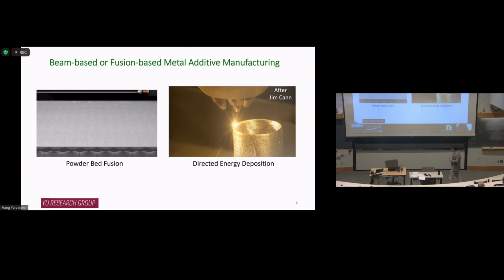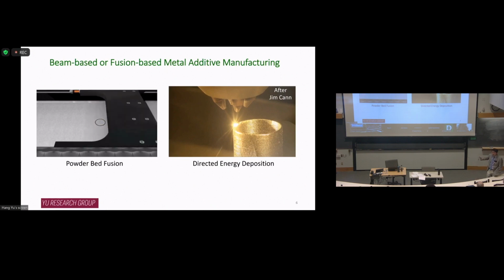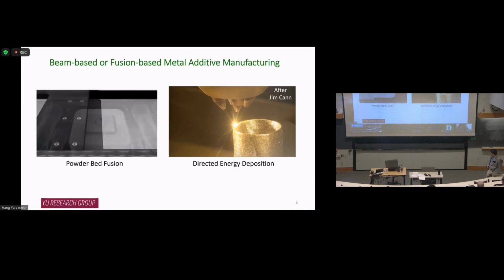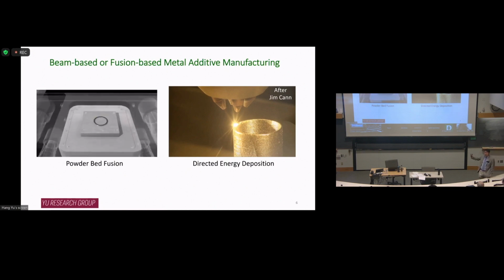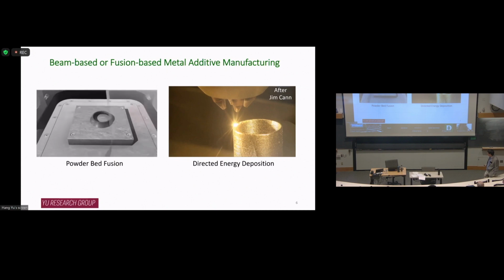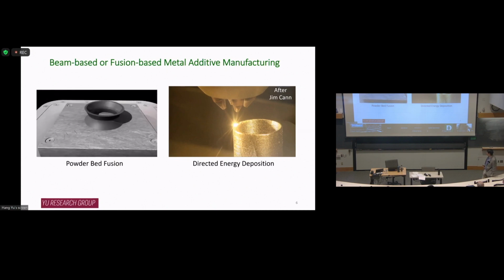So I have 2 examples here, like a small animation showing what's going on. The first one is powder bed fusion. So that's a layer of powder, and you apply a laser. You can generate a pattern in this layer. And then you have to lay out another layer of powder. Repeat this process with a different material pattern, depending on your G code. Repeat this process layer by layer, and you can make 3D components. Of course, the material pattern in each layer does not need to be the same, right? That's why you make 3D components. But that's a very simple illustration. So this is powder bed fusion: you have a powder, you apply a laser beam to generate a material pattern.